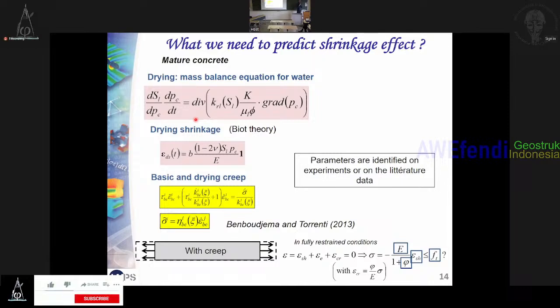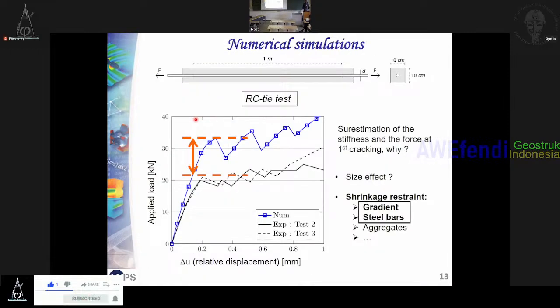We measured the weight loss evolution. At that time we did not put a sensor inside like you have done, and it's better, I agree with you, to put sensors inside to capture the gradient. It's possible to capture a gradient using this model, but is it the correct one? I cannot say it's a good one. That's why I put here effect of size. It is not a size effect regarding tensile strength, but also regarding drying. By identification and then simulation, we hope we didn't make too many mistakes. Yes, I'm sure you didn't.